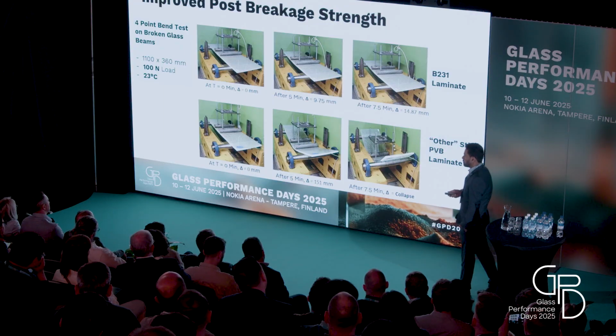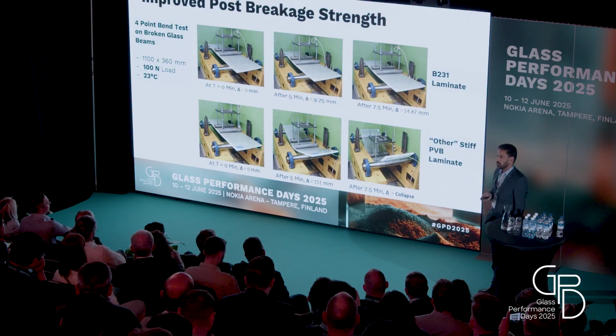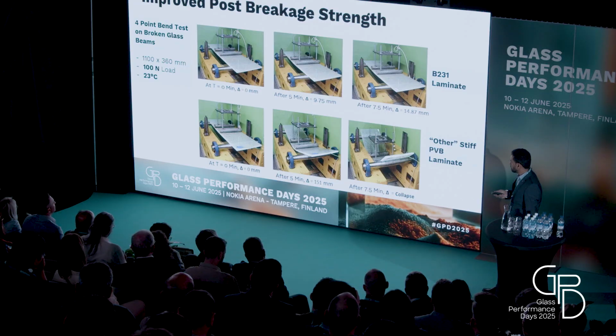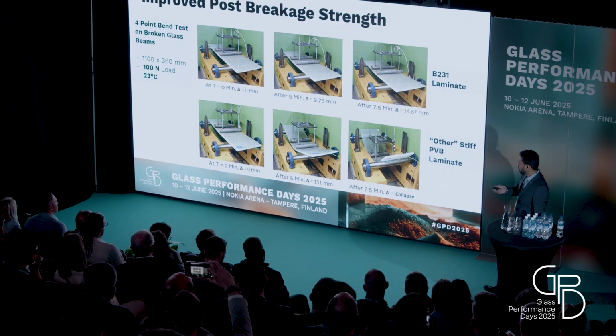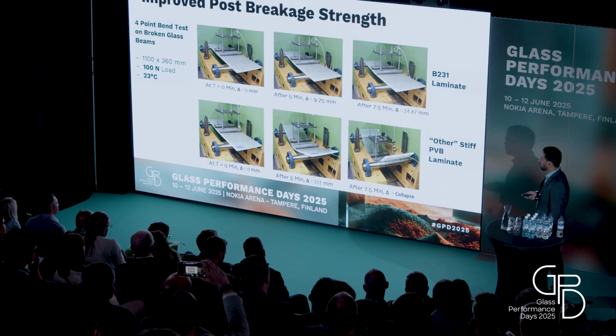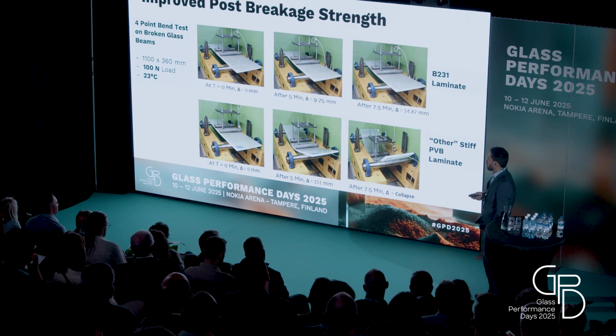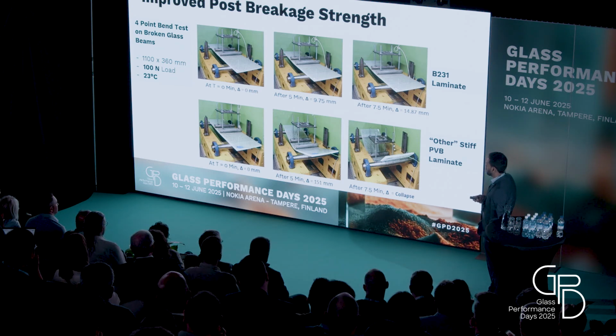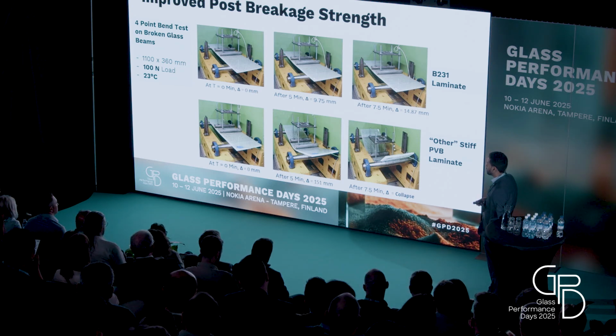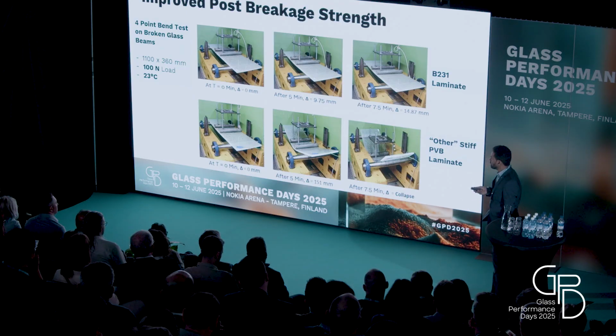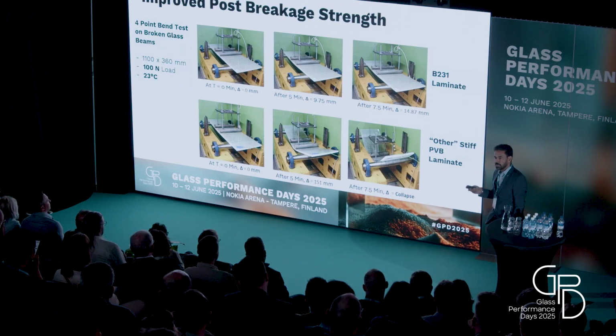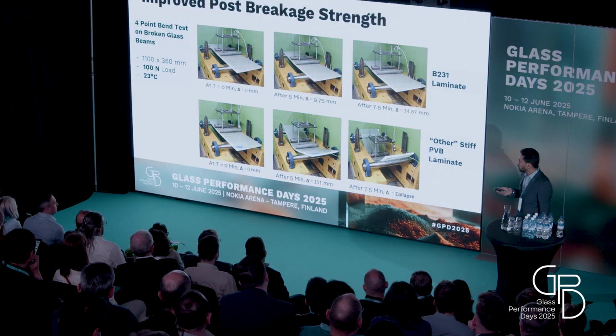And also, there is an interest for structural engineers to look at the post-breakage performance of the laminates. So my colleague Ingo Stelger was involved in post-breakage testing on glass beams made with tempered glass. These are fully tempered glasses, and we intentionally broke the glass, and these were subjected to a point load.